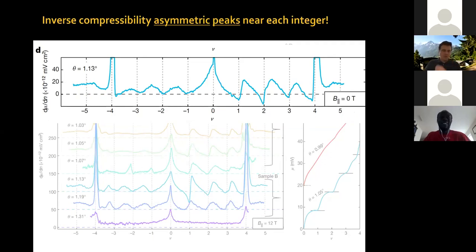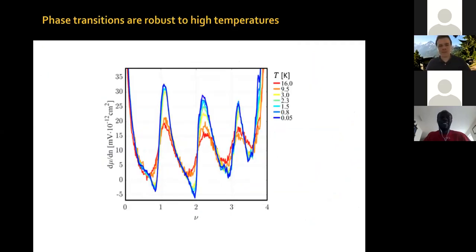Now, what do these peaks mean? How do we interpret this thing, okay? We interpret it, oh, and by the way, let me just mention before I tell you about the interpretation, here you can see this inverse compressibility versus filling factor, and now you can look at the temperature dependence. The maximum temperature for the red curves in this data is 16 Kelvin, and you can see that you still have these peaks happening, okay, near each integer.